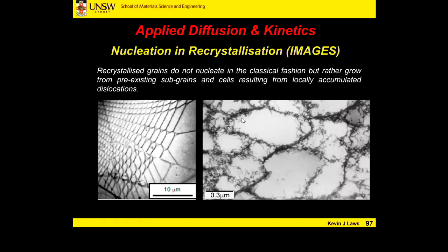One of these subcells, maybe one of these ones over here, we can see we've actually got a grain that started to recrystallize within this other major subcell. So that's how they form. We need those dislocations, we need them to tangle up and form those subcells within our grain. Those subcells start to realign and reorientate themselves, dislocations are cancelled within their core, and they start to grow as a deformation-free crystal.